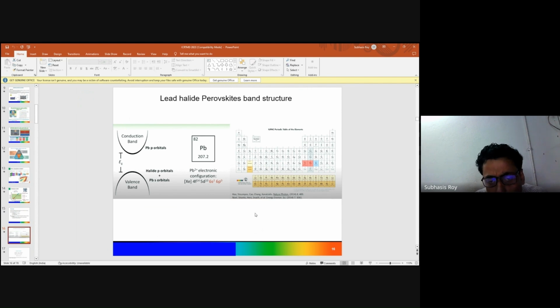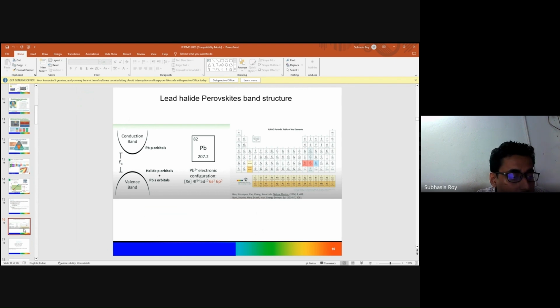So the lead material is very important in the case of solar cells, giving very good efficiency because of its band structure. If you see the periodic table, when you go apart from lead, tin and germanium are moisture sensitive, and when you go to the bottom, they are also radioactive. And when we go to the left side, the valence of these materials is different, so defect formation happens. So selecting the replacement of the lead material is very important, so that it gives a properly stable, sustainable perovskite solar cell.